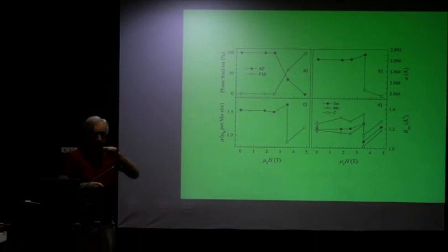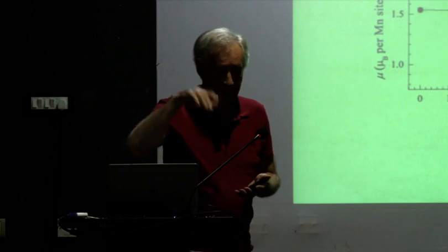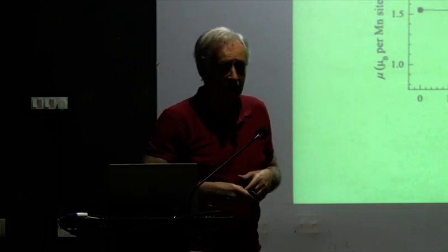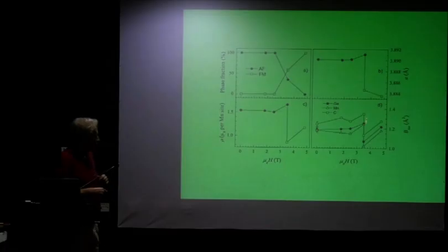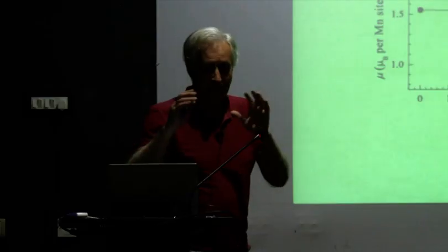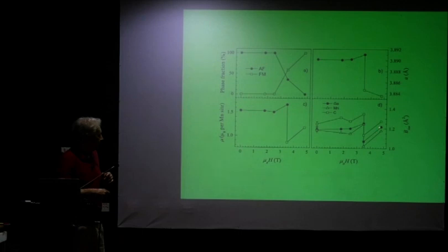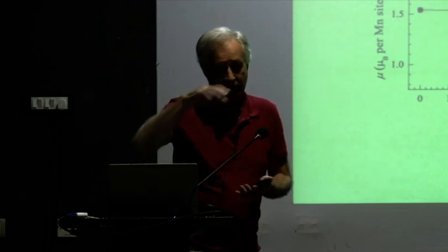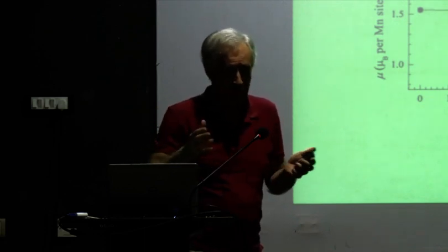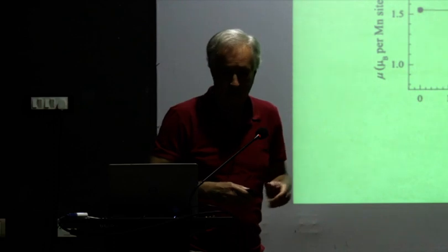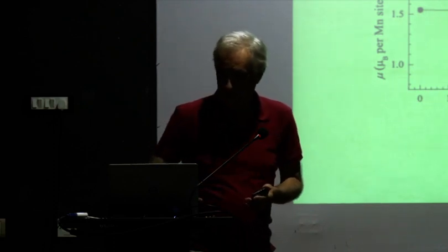Normally, this should be spherical because the atom can move in all directions equally well. But when you get into the strained state, suddenly you have some confinement. In certain directions it's more difficult to move. And then when you increase the field in the ferromagnetic state, the original value is recovered. It should be, so that the vibrations are spherically symmetric. This just gives you an indication that there is some strain involved at the transition point.